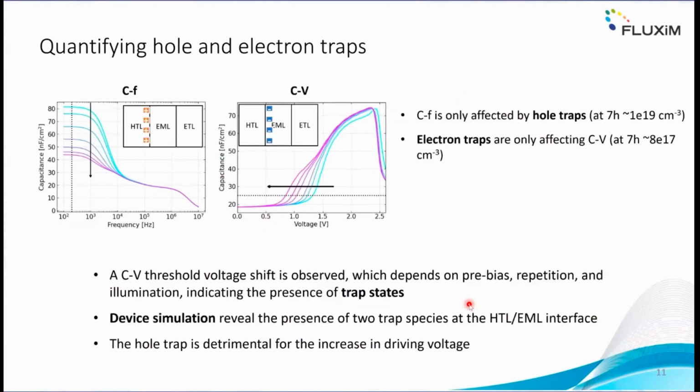Now, long story short, we actually were able to reproduce this interesting phenomena. So the first phenomenon is this shift of this plateau to the left, which we are able to describe by introducing hole traps in the EML.